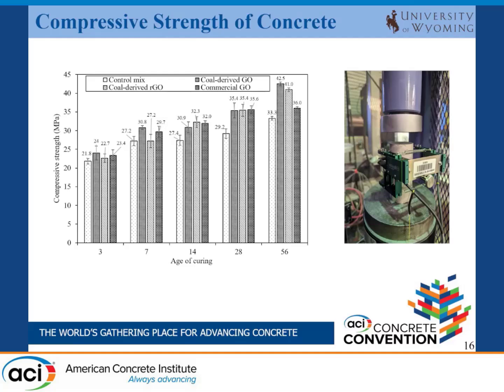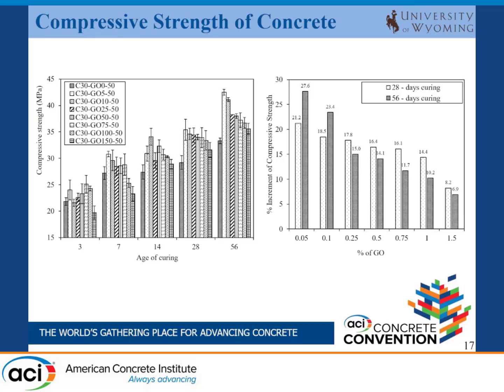Till that point, we confirmed that our graphene oxide has some improvement or comparable results with the commercial graphene oxide. After that, we chose our graphene oxide and expanded the range from 0.05 to 1.5% of graphene oxide in the concrete. And interestingly, we found that whatever the percentage we use in the concrete, there is at least some improvement in every percentage of graphene oxide. That means it has some impact on the concrete. And in most of the region, at 28 and 56 days, the highest strengths come at 0.05 to 0.1% of graphene oxide in concrete, which aligns with the previous studies of the researchers.